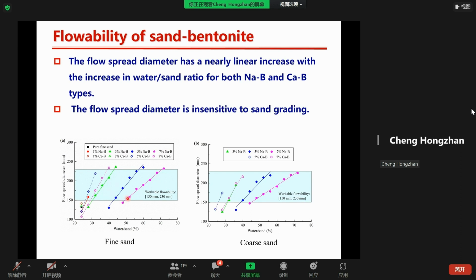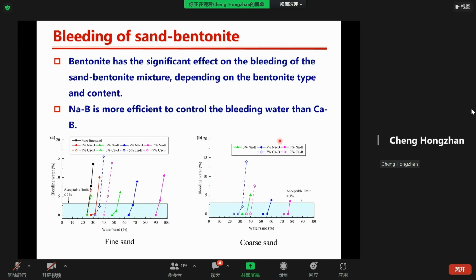Moreover, the flow spread diameter saw a linear increase with the increase in the water to sand ratio for both sands and both types of bentonite. Comparing these two figures, the flow spread diameter is insensitive to the sand grading. Okay, here is the bleeding result. In general, the acceptable bleeding water should be less than 3.